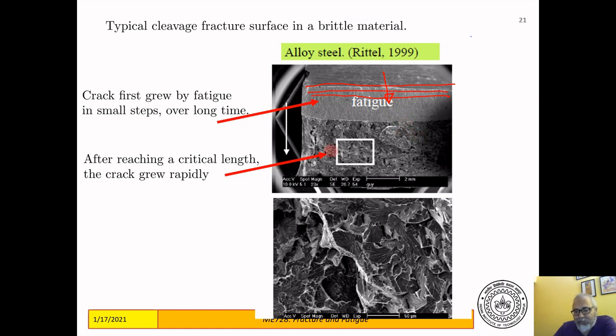So the crack is propagating in this direction, and first it propagates by fatigue, which leads to a relatively clean surface. Then you have a messy surface here, and this messy surface at higher magnification looks like this. Look at the scale again. The scale is 50 microns, so this length is 50 microns. So this would be around 200 microns maybe. So this messy surface is what you have in this. The changeover from this clean, striated fatigue surface to this messy surface tells you that the crack grew by fatigue up to here, and then it grew catastrophically, and because this is a brittle material, it leads to this kind of a messy surface, which is a typical signature of brittle fracture, also called cleavage fracture.